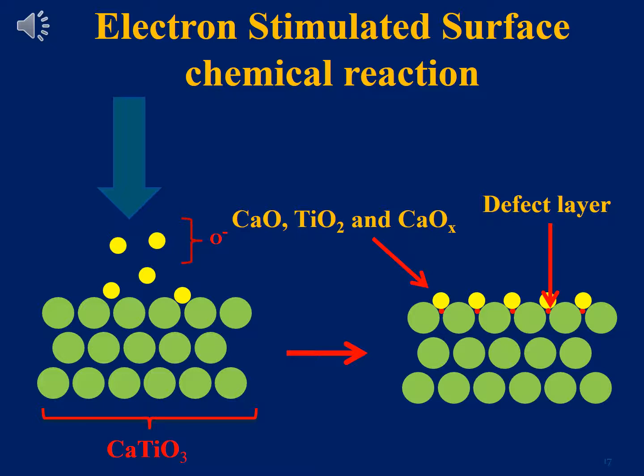Now, when we do the Monte Carlo simulations, which we are not covering in this presentation, we pick up that at the interface of the new oxide and our sample, a defect forms, acting as a quenching center, which is promoted by the formation of the new oxide layers on top of our materials, and which consequently quenches the luminescence intensity in our materials.